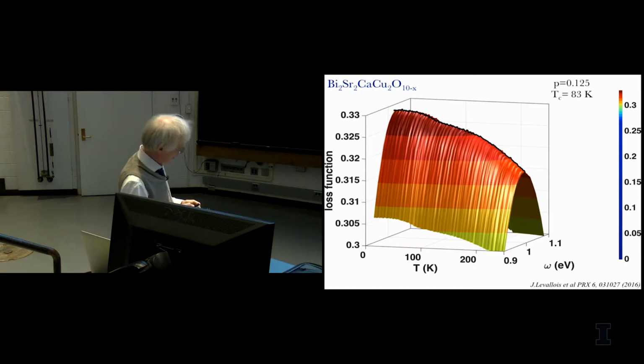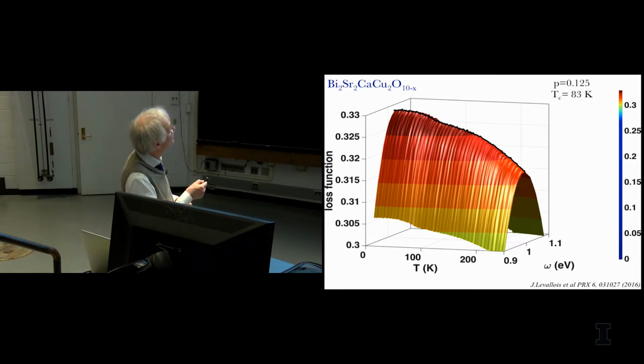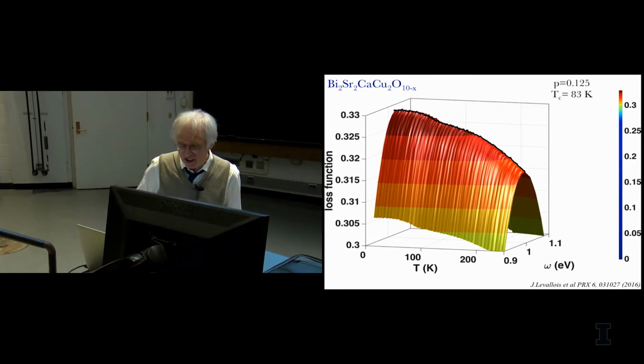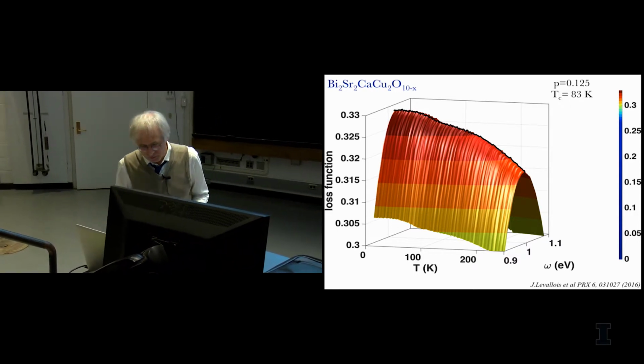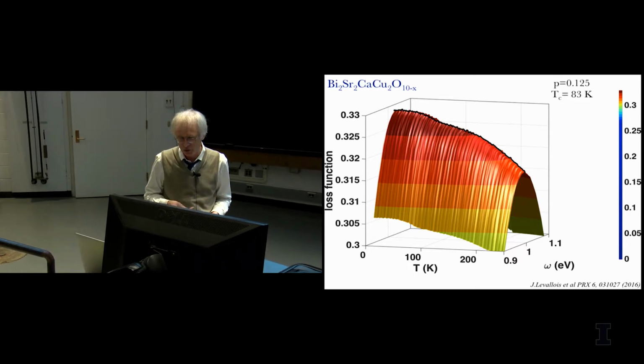If you just blow it up a little bit on the top, you see it better. That is actually a little extra nudge over there. So you see that the entire peak is actually getting a bit more intense going into the superconducting phase, because this is where Tc is for this sample. So that would actually correspond to an increase of Coulomb energy, by the way, in this case, just using that formula.